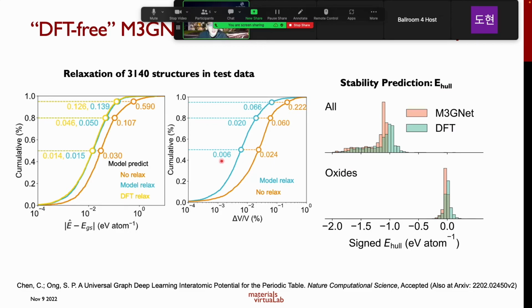With this M3GNet universal potential, what we can do today is DFT-free relaxation of crystal structures. We have a test data set of about 3,000 structures with DFT relaxations. For these 3,000 structures, we can get predicted ground state energies that are very, very close to the DFT ground state energies. The relaxed volumes of our crystals are also very close, typically within 1 to 2% of the DFT final relaxed volumes.